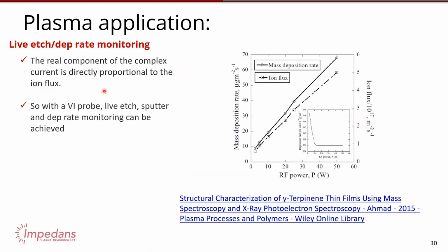What about the current? With the current, you can actually get ion flux, right? When a VI probe is measuring current, it's actually a complex current. If you think about it, there's a real and imaginary component, or maybe you can think of it as an active and reactive component. I'm not sure what the words are, but essentially the current it measures has a complex value, and the real component of the complex value is basically the real DC current passing through the probe. That DC current is obviously directly related to the ions hitting the surface. So more ions hitting the surface, higher DC current.